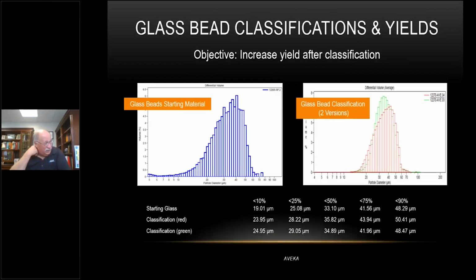Now let's just consider classification for a second. There's no bead milling or jet milling in this particular case. Basically we're taking nice spherical glass beads, and we want to classify out and get that distribution, get rid of that fine cut again, because we didn't want the fines. But what we want to show here is how we can optimize the yield after classification. The tighter we try to make our distribution, the more product we're going to let go. So here the starting glass has a D50 of 33 microns, a D10 of 19 and a D90 of 48 microns, as you can see on this slide.